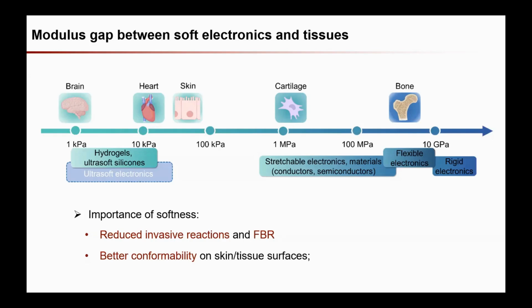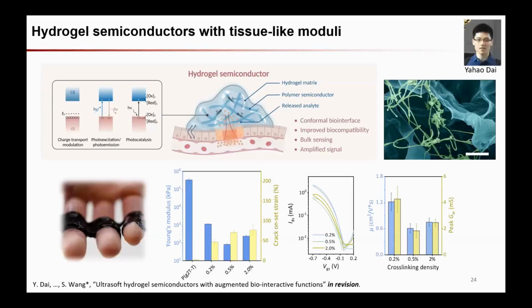To do this, one work that we had been doing started from the material level, to make the semiconducting polymer into a hydrogel design. The main challenge we had to solve is that semiconducting polymers, like 99% of them, especially the high-performing ones, are not water soluble. So their design is not compatible with the typical processing method for making hydrogels. To solve this challenge, we came up with a new processing method that led us to make a double network semiconducting polymer hydrogel.